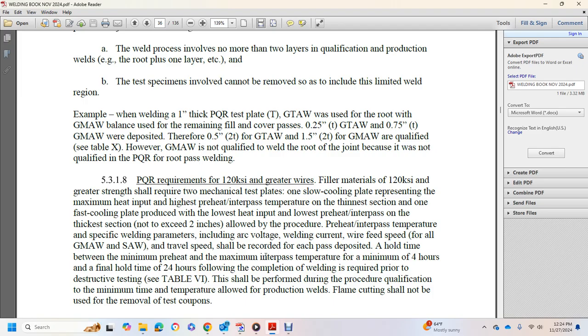Allowed with the preheat and interpass temperature, the specific welding parameters include arc volts, welding current, and wire feed speed for all gas metal arc or submerged arc welding, and welding travel speed should be recorded with each pass deposited. The time between the minimum preheat and maximum interpass temperature, the minimum 4 hours with the final hold time of 24 hours following the completion of the welding, is required prior to the destructive testing, Table 6.